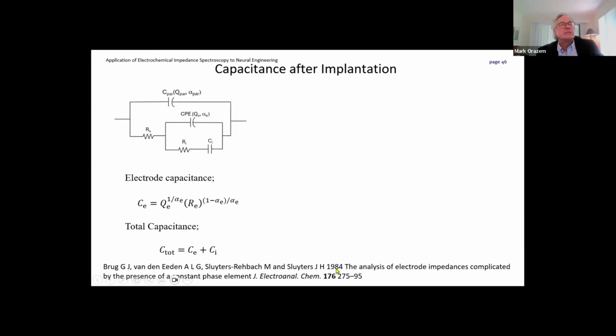And this was published in 1984. And basically, this is saying that this constant phase element is due to a surface distribution of time constants. And effectively, we can show that this is going to be the formula that we need to use. Re, this is the ohmic resistance, which is this guy over here. And then we have alpha and Q that we get from this model. The total capacitance then is the sum of this and the capacitance that we get from the iridium oxidation and